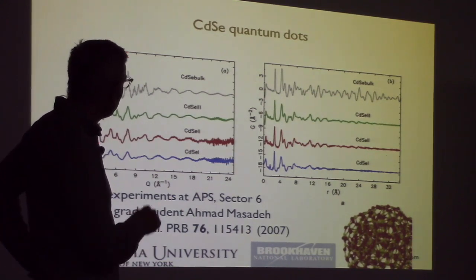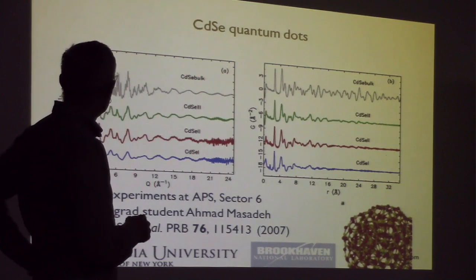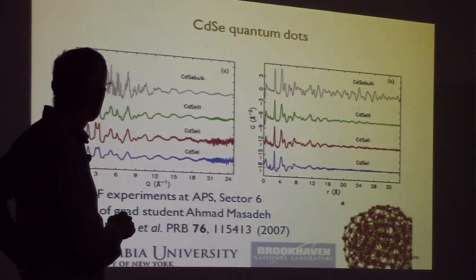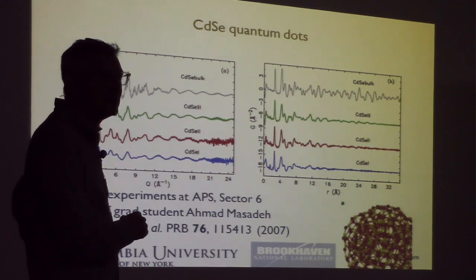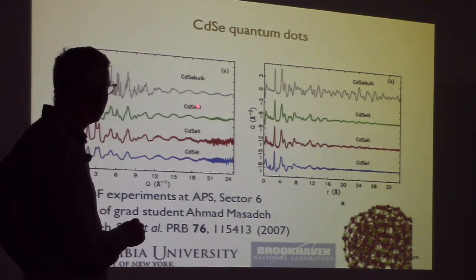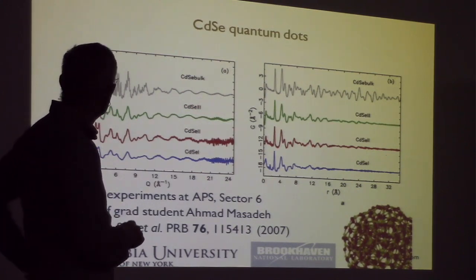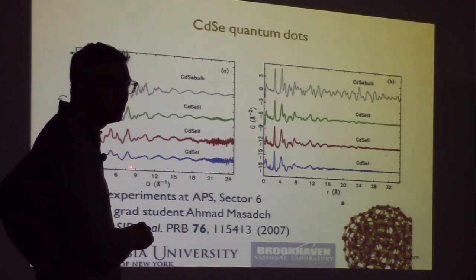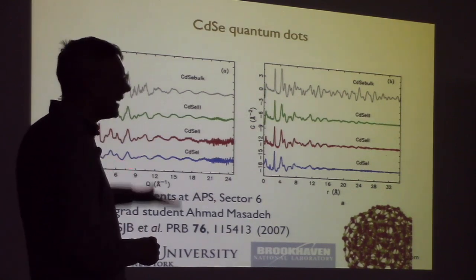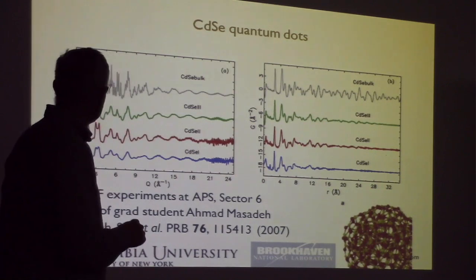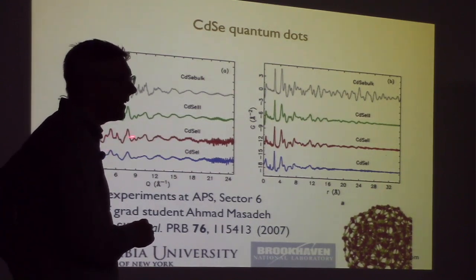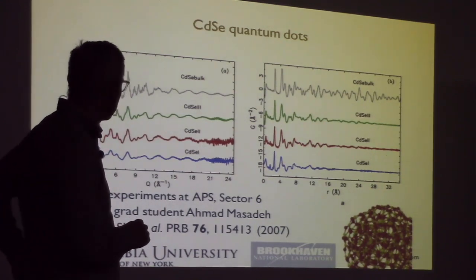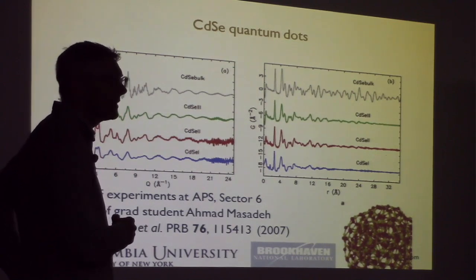And this is the diffraction pattern over here. If you look at the diffraction pattern, the bulk material has very sharp Bragg peaks. And what happens to the diffraction pattern as you get to these small nanoparticles, and as the nanoparticles get smaller, these diffraction peaks get broader and broader and broader. They also get lower. They've been rescaled. So that's characteristic of the finite size effect. Small nanoparticles, your diffraction peaks get broad.